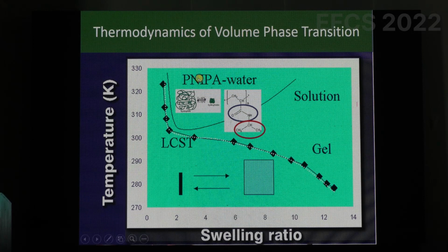Now, if you take this polymer and you dissolve it in water, so it's a non-cross-linked polymer, think of it as a dilute polymer solution, and this is a polymer which is fairly high molecular weight. It loves water, so it swells, with a lot of water around it, and that happens at lower temperatures. At lower temperatures, it loves water, and then as you start heating up the gel, so as you go up in this axis, it phase separates. So if I'm starting anywhere in this region, it is a single phase solution,